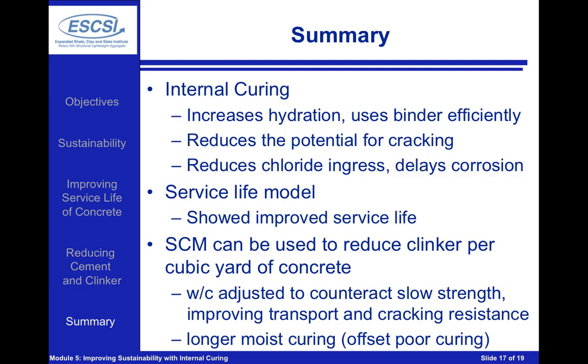So in summary, what we've seen in this module is that internal curing works by increasing the hydration of the cement and supplementary materials. It's going to allow us to use our binder more efficiently, which means that this is going to be working very well when we start to talk about supplementary materials or Portland limestone cements. Internal curing is going to provide us the ability to reduce the potential for cracking, and this is going to be very important in the systems as well. We're going to be able to reduce chloride ingress in those systems because we've hydrated more of the system and we've disconnected more of the connected interfacial transition zones.